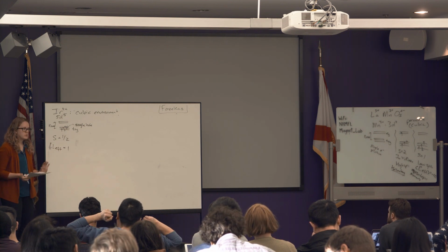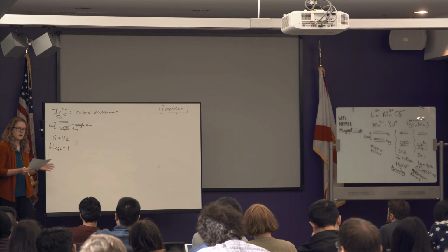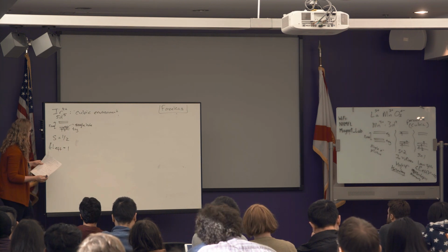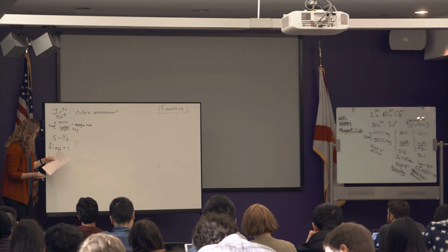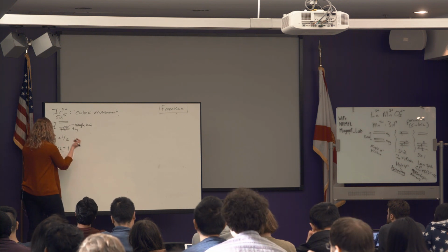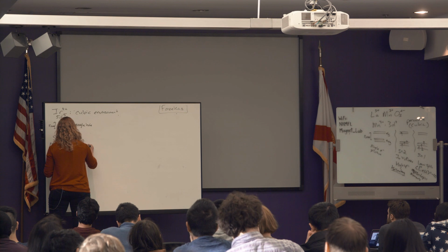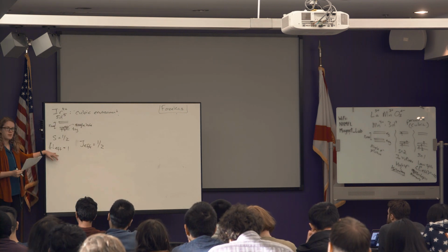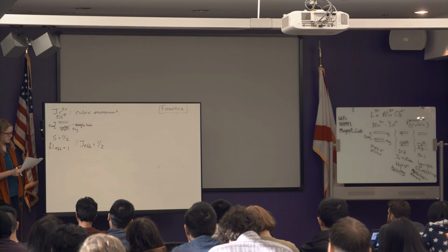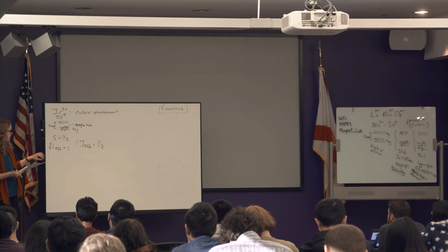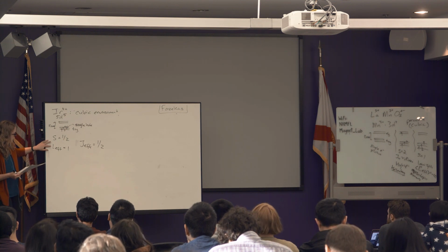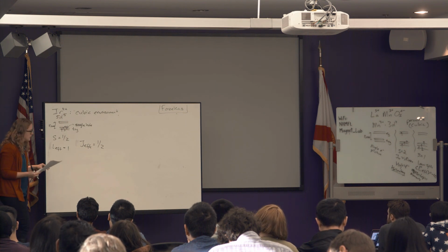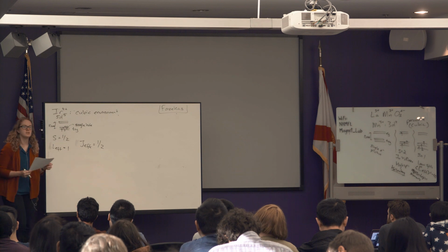Hund's rules with the spin-orbit coupling still work the same, except I'm thinking of a hole instead of an electron. So you end up with a J effective of 1/2. Here I'm just using this fake angular momentum, but real spin. You can actually calculate what the angular momentum in this particular state is, but it's better to think of it as a J effective 1/2.